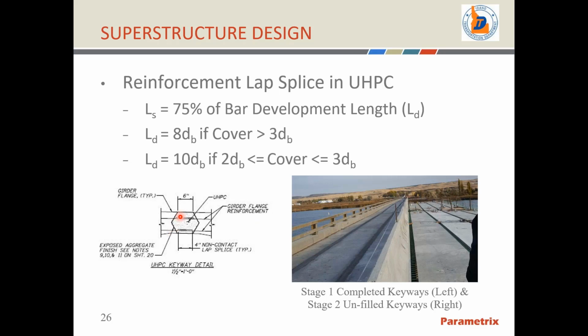As I mentioned before, the UHPC bonds well to the existing precast surface if it's prepped correctly. The best way to prep it correctly is you need to get an exposed aggregate finish on the inside face of that keyway. A good way to do so is to use a retarder on the form, and then when they cast the member and remove it from the form, they go ahead and power wash it and expose that aggregate, and it gives a nice exposed aggregate for that UHPC material to bond to.